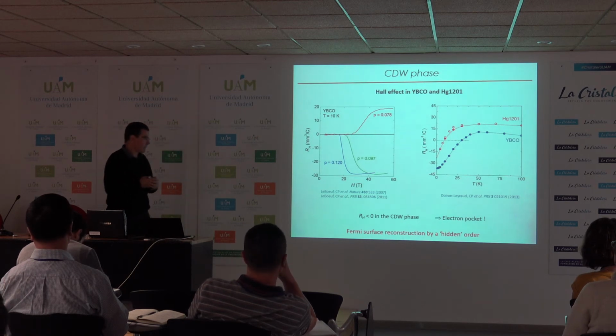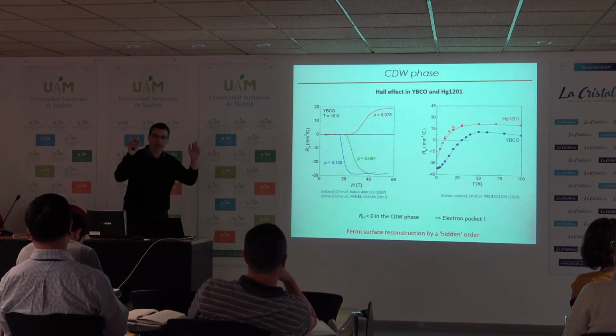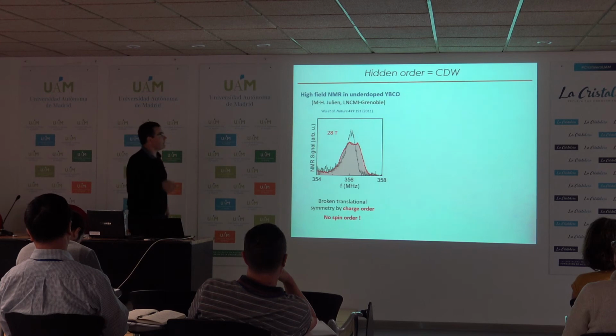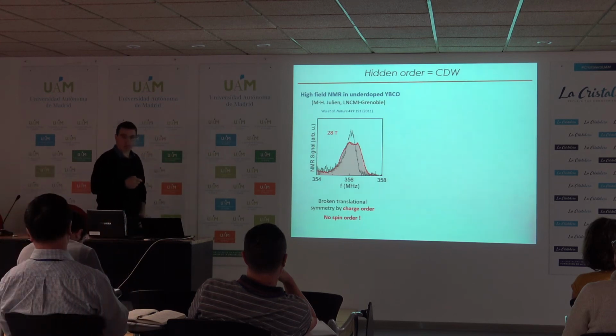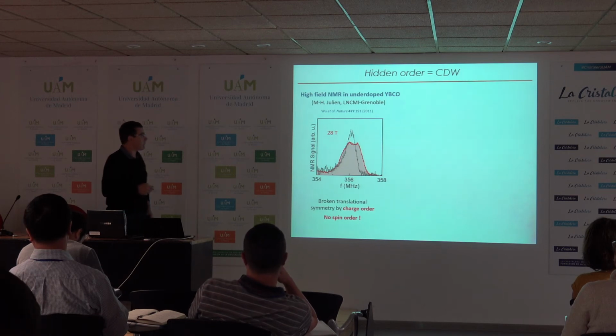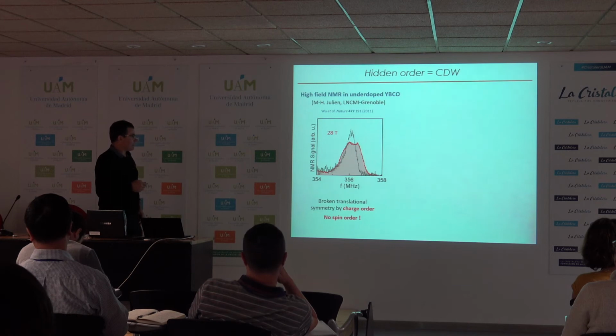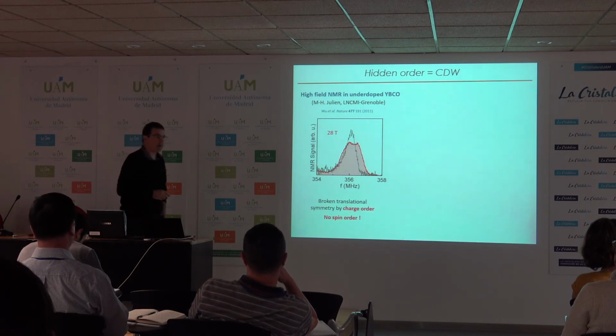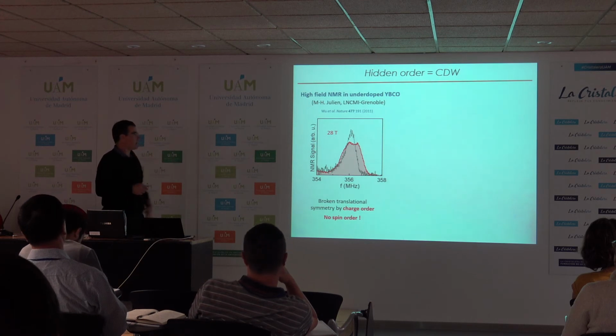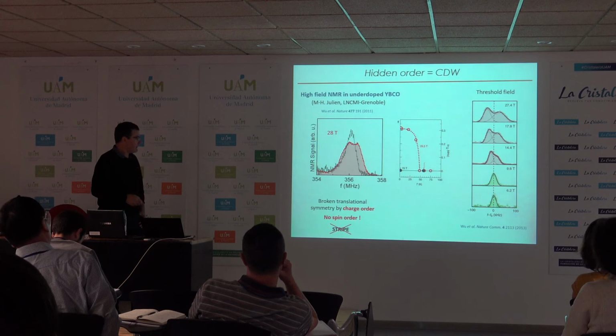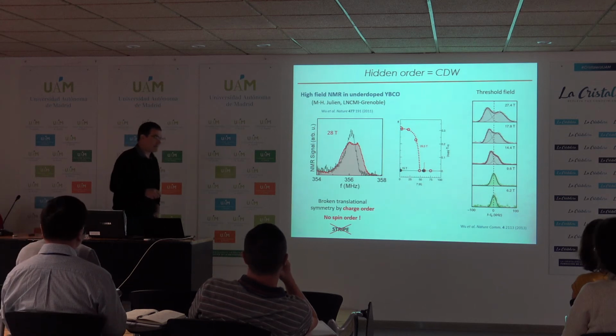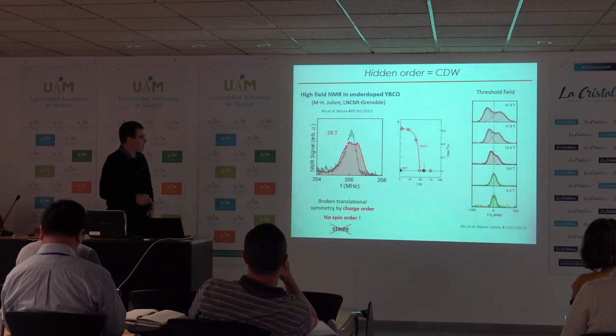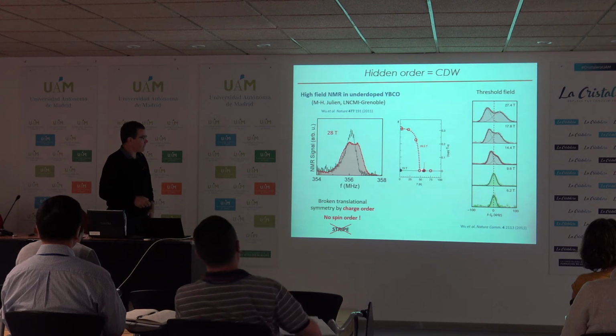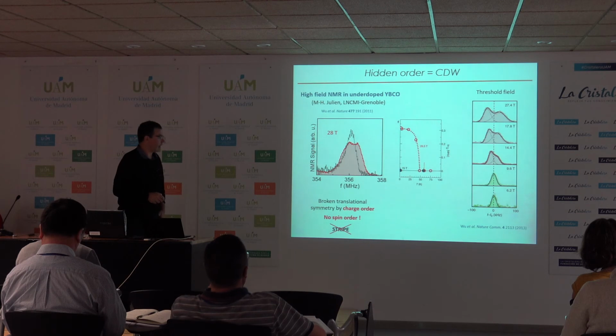At this time, we called it a Fermi surface reconstruction by some sort of hidden order. And this hidden order was discovered by my colleague Marc-Henri Julien by performing NMR measurements in underdoped YBCO, where basically they showed that there is a splitting of a particular NMR line, observed only in high magnetic field and below a certain temperature. There is no spin order, meaning that this is not a stripe order as has been discovered in the LSCO family. So here I show the splitting of this line versus temperature. You see that you observe it only below 50 Kelvin at high magnetic field.